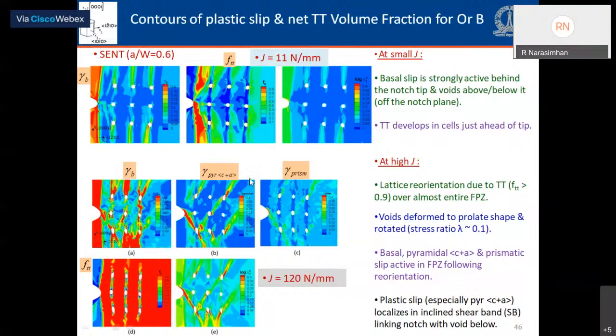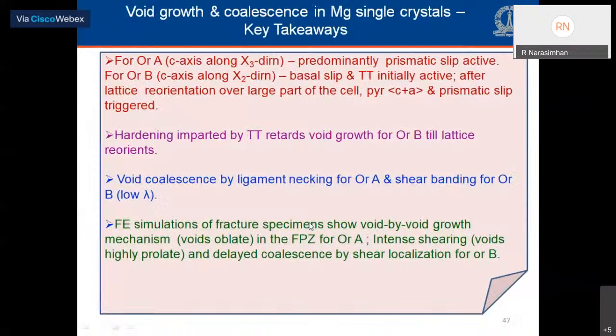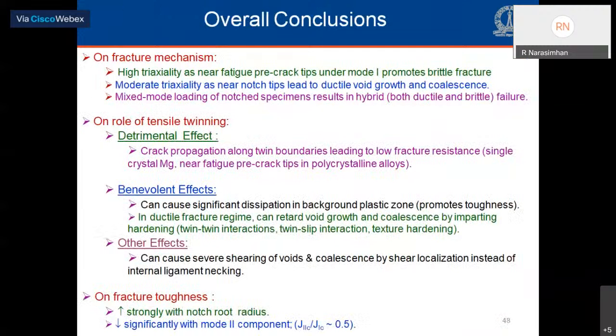You can make that out in the right side middle image, which are forming as shear bands crisscrossing across the fracture process zone. And this leads to intense shearing. Some of the voids here have deformed into highly prolate shapes, and coalescence would take place by shear localization. Now, these are some of the key takeaways from this part of our work. Instead of going through this in greater detail, let me conclude this talk, since we have reached the 1 hour mark, by taking an overall perspective of what we can understand from our work, whatever we have done till now.